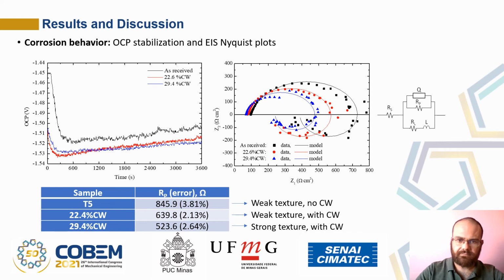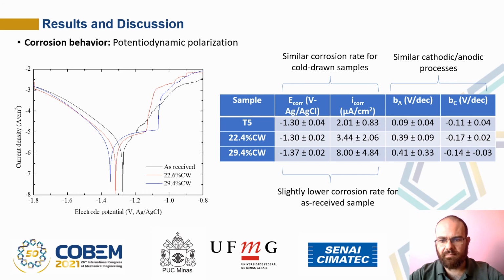What we see here are the OCP results showing that samples more or less stabilize after 1 hour exposure to the electrolyte, and the Nyquist plots of the impedance results, which show a slightly larger capacitive arc for the as received sample, which indicates a larger value of the polarization resistance, so a lower corrosion rate is expected for the T5 condition. The polarization diagrams did not reveal any significant difference between the samples. Similar values for the corrosion potential and the current density. What can be said is that we have a slightly lower corrosion rate for the as received sample, since it has the lowest value of corrosion current density. But the differences are small.